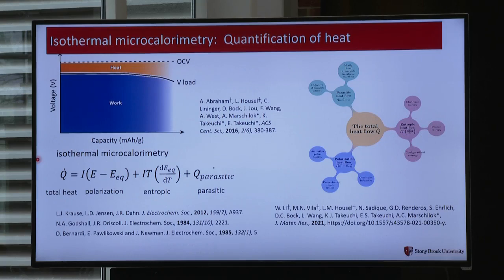So we used a method called isothermal microcalorimetry. We're keeping the temperature fixed and measuring the heat dissipation. We analyzed the data according to the equation that I'm showing you. We determined the heat dissipation due to polarization, meaning basically voltage drop. We determined the entropic contribution. And what we were interested in was the parasitic heat, meaning everything we can't account for through polarization or entropy.